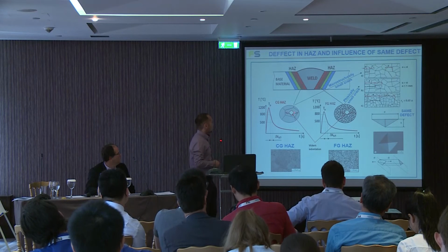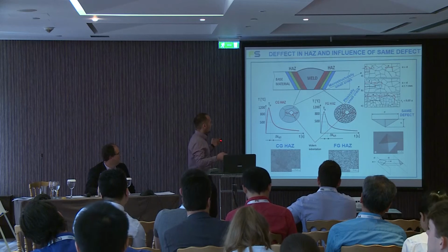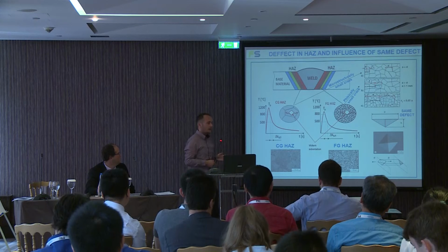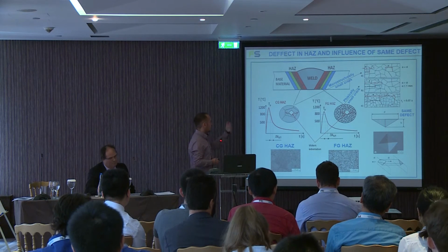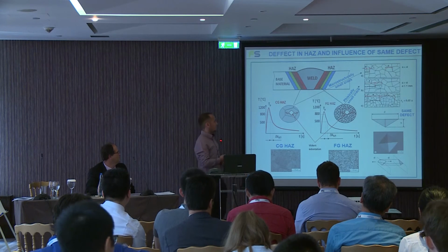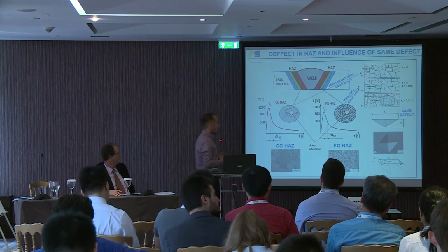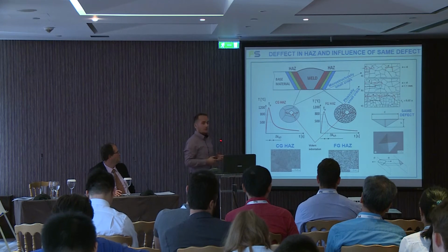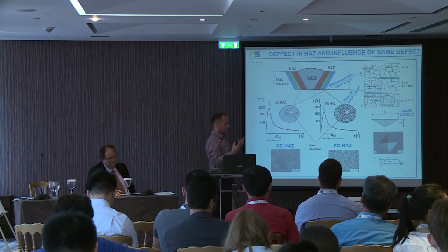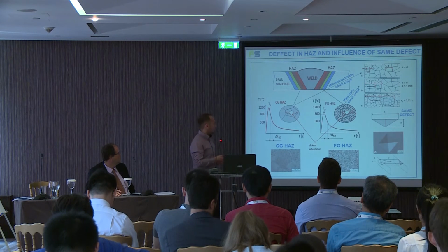So the crack begins and propagates till it achieves the border of the grains, and after that there is a barrier which doesn't allow it to move forward. In the second case, we have fine grain heat affected zone where the Vickers indentation or artificial defect is bigger than 2 or 3 grains, and so the grain boundary is too weak to resist the crack propagation.